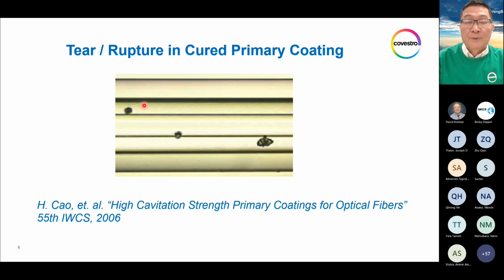This is a microscope picture of a coated optical fiber. So this is the glass cladding, then the primary coating layer, then the secondary coating layer. We observed a tear or rupture in the primary coating layer, because if the coating is not formulated properly, then with the reduction of modulus, which is a mechanical property, the strength could suffer. When the strength reduces along with the mechanical property, a tear or rupture could be the result.